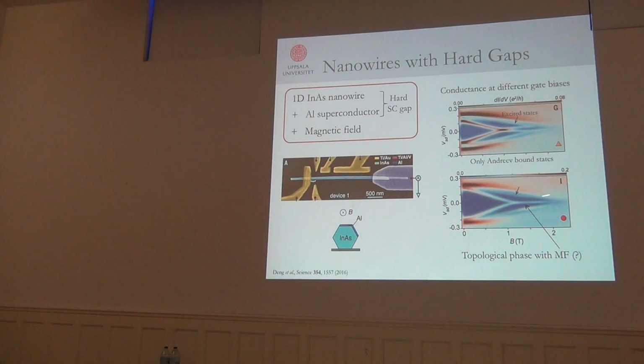The window here for having superconductivity and still enough magnetic field to be in a topological phase is not a trivial condition to fit. And in fact, the spin-orbit coupling is good in this case, because if you take your spin singlet superconductor and you apply a Zeeman field, you will effectively kill superconductivity just when you reach a topological phase transition. The spin-orbit coupling will cant your moments out of plane and make superconductivity survive this magnetic field, but still the window is not huge.